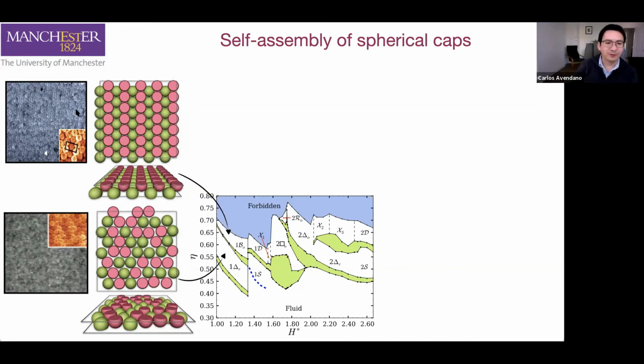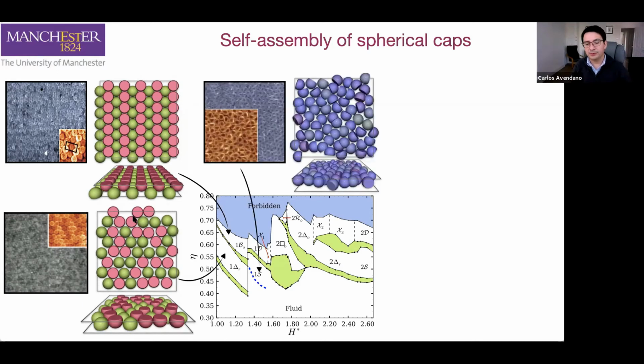Now, something very funny will happen when we increase the distance between the two plates to be compatible to the size of the cross section of these particles. Now they will be able to rotate. So this is the first time that the particles will be able to rotate. And what we observe is that they don't want to adopt anymore the configuration of either pointing up or pointing down, but rather the flat facet is pointing parallel to the confinement. So this is what the experimental group calls a side phase. And again, that structure is completely in agreement with what they observe in the experiments.